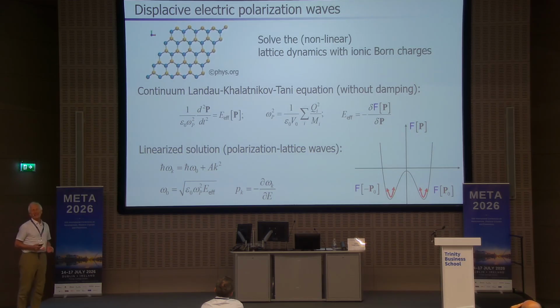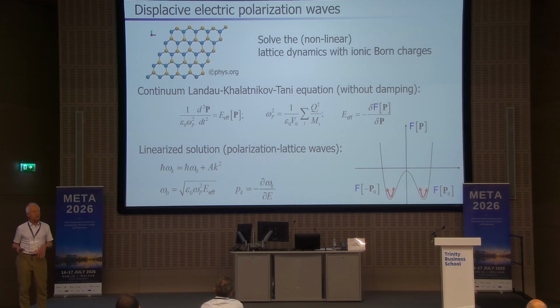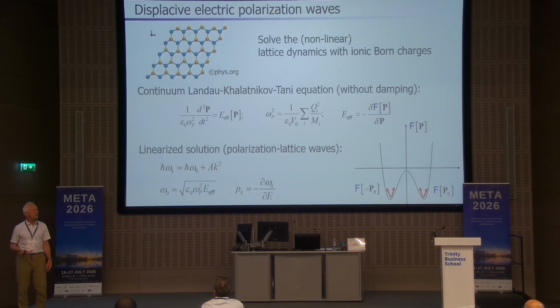The driving force here is not an effective magnetic field, but an effective electric field. And also this is a functional derivative of the free energy I introduced before. Now, the simple solution gives you again a quadratic dispersion, like indicated here. And this omega 0 is now in the terahertz regime.